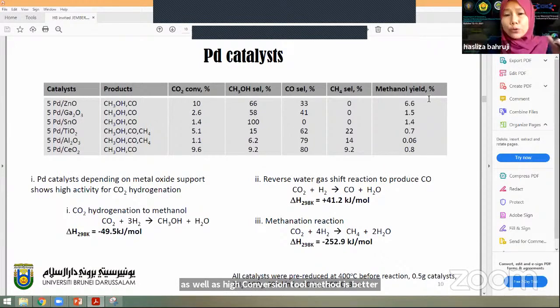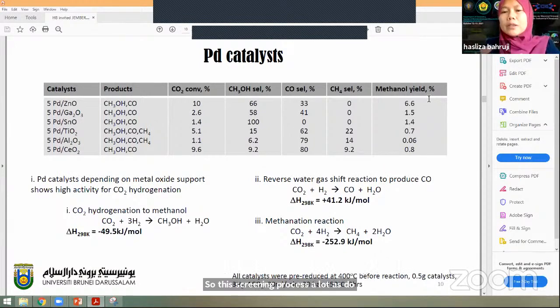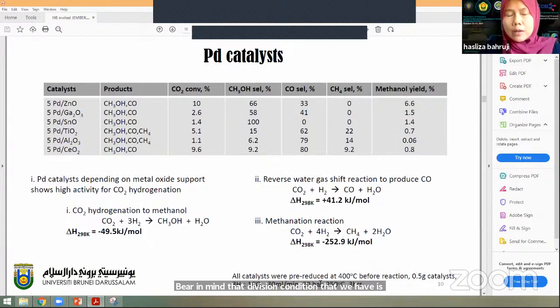So this screening process allows us to easily pinpoint the best metal oxide that can be further investigated to improve the selectivity towards methanol under mild reaction conditions. Bear in mind that the reaction pressure that we have is only 20 bar, which is quite mild compared to industrial conditions, which are normally 50 bar.